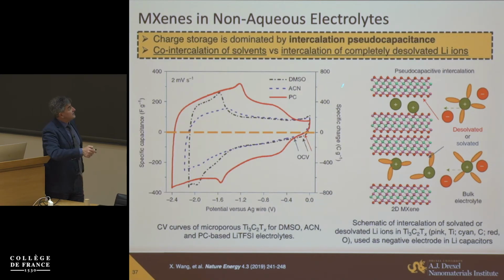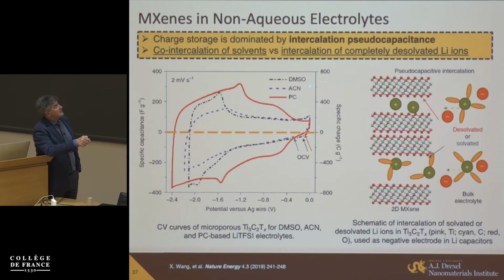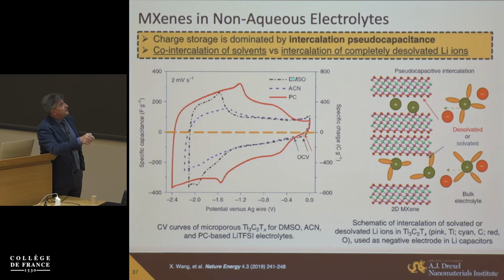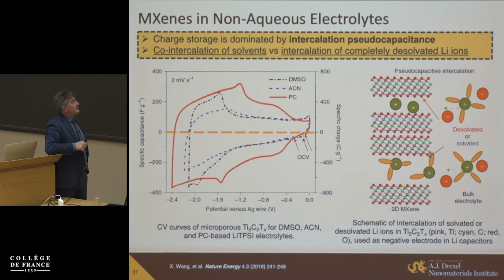And we looked at capacitive energy storage with titanium carbide Ti3C2 MXene in lithium TFSI with solvents DMSO, acetonitrile, and PC. And actually, a precursor to this was an electrolyte genome work done by many in the US, predicting, for example, that the mobility of lithium in acetonitrile in this salt solution will be an order of magnitude higher compared to PC and DMSO, and we wanted to look at whether it would help us get good results.